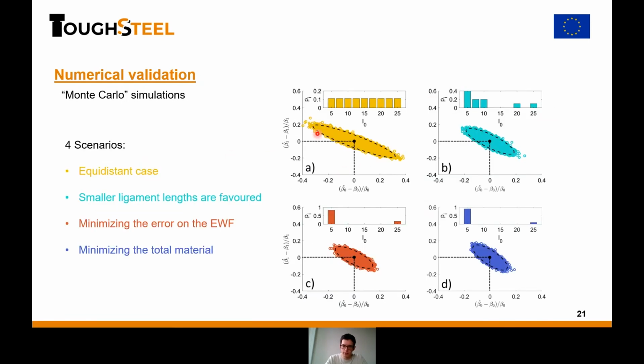And so I summarize this in this graph. Again, I have 4 different scenarios. I will go through first what is displayed on these figures. Basically, it's the estimators minus the true value, normalized by the true value. So the larger the spread around each axis, the larger the error or potential error you make using this type of scenario. The x-axis is for the intercept, so it corresponds to the essential work of fracture, and the y-axis is the slope of the regression. We see in yellow the equidistant case, where the spread on the slope is quite tight, which is quite nice, but on the intercept it is quite large.